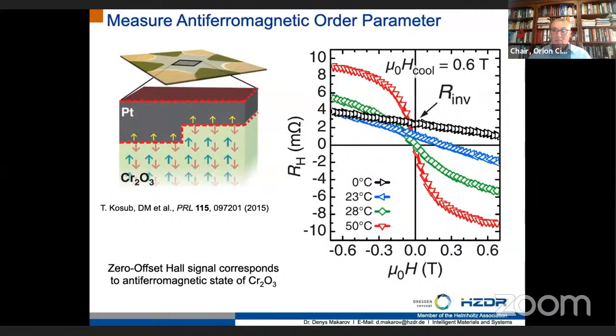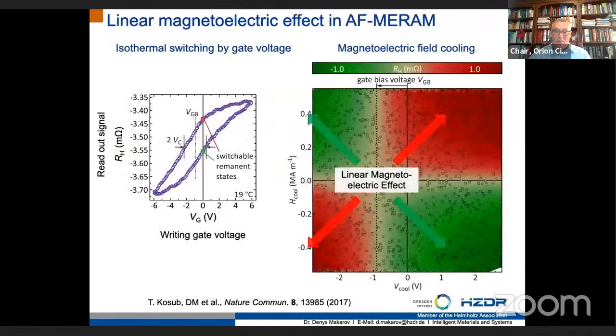In this case, one has to monitor the field invariant transversal resistance after the sample was exposed to a specific cooling field or combined magnetoelectric cooling field. What you can see on this slide is a linear magnetoelectric effect in the thin film of chromium oxide, which is encoded in a Hall resistance, transversal resistance, which is measured on this material upon cooling the sample through the Néel temperature in magnetic and electric field.